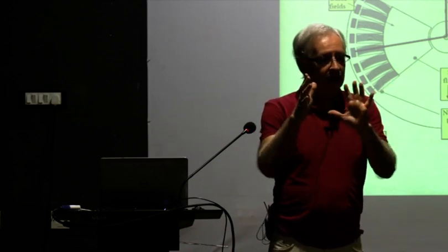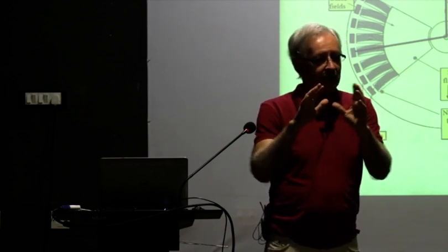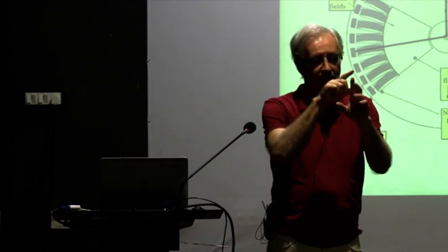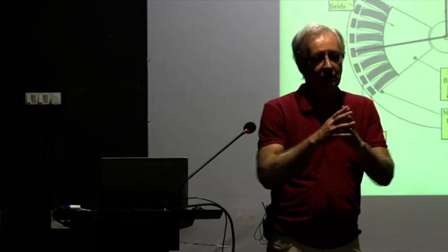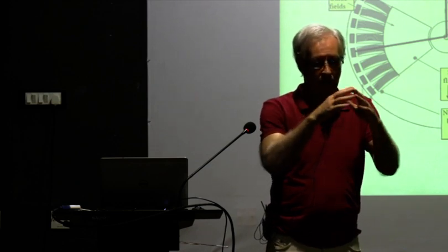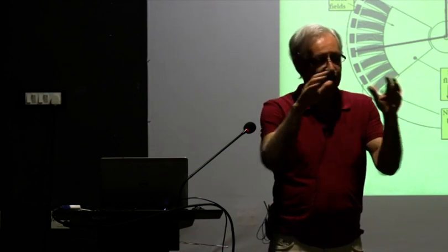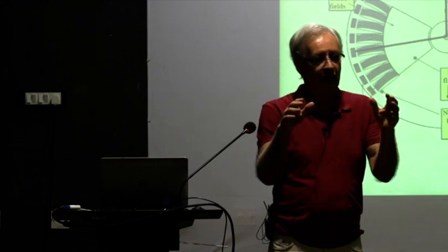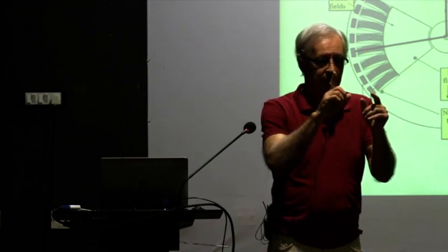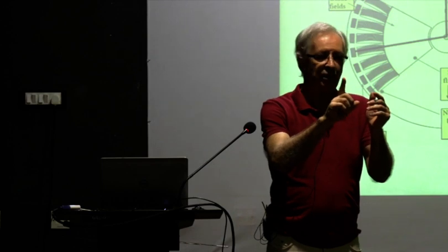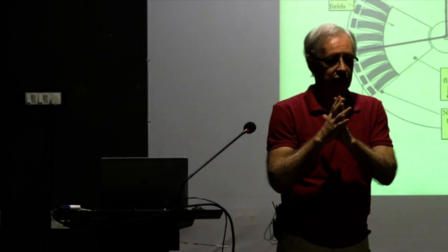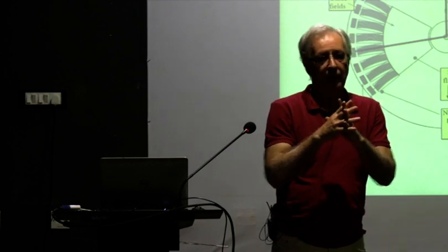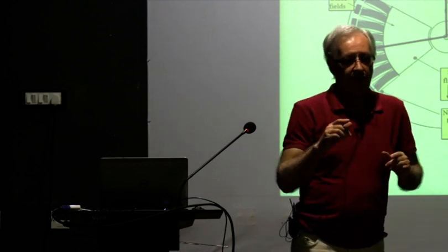If there are some deviations from the ideal magnetic structure, then these peaks can broaden. And they can broaden so much that they will be smeared out, showing a shoulder-like feature, but the center position of that shoulder would still be that half Q, more or less. This is for an antiferromagnet.